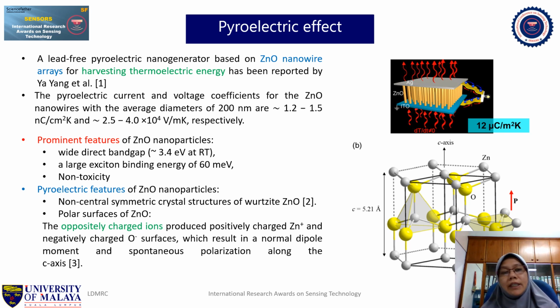Ya Yang et al. have reported that thermoelectric energy can be harvested from zinc oxide nanowire arrays. From these zinc oxide nanowire arrays, he has obtained pyroelectric current as much as 1.2 to 1.5 nanocoulomb per centimeter square Kelvin, with voltage coefficients of 2.5 to 4 times 10 to the 4 volt per meter Kelvin respectively.